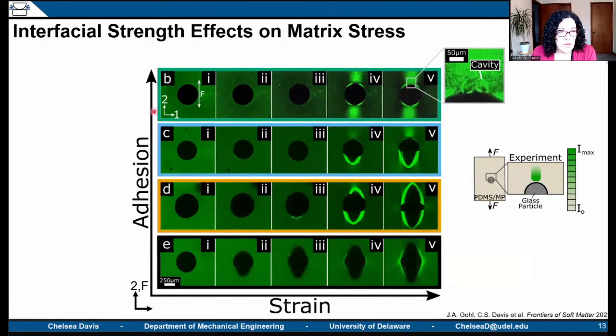And here I kind of glossed through it, but we got even higher adhesion to the point where we started observing the formation of cavities in the material, which is very different from this large scale interfacial separation. So for now, we haven't published our quantification of adhesion, and we're just using these as qualitative descriptors. All right, thank you.